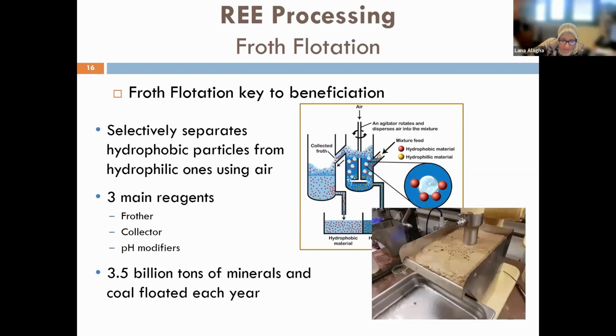Again, this is a picture showing the froth flotation process. This is the froth. You can call it concentrate. This froth consists of solids, consists of water, and you can still see the air bubbles. And by the way, the shape of the froth can tell you about how good the selectivity of the flotation process is. Because if you have, for example, ultrafine material, it may entrain into the froth layer, not as a result of true flotation, but as a result of mechanical entrainment because of the small size. So usually, if the froth has hexagonal shape, then it is of good quality. If it is more like a foam, then it has a poor quality.